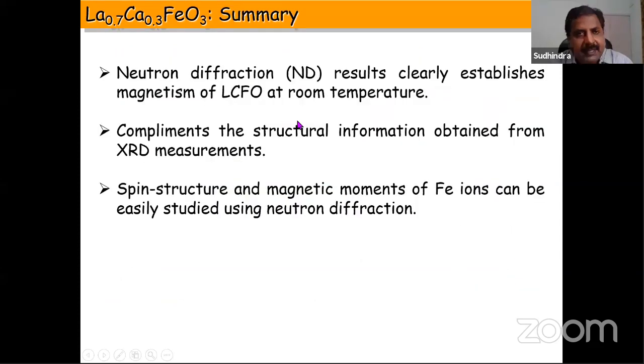So to summarize this part, I can say that the neutron diffraction clearly establishes that LCFO was magnetic at room temperature. There's no impurity in that. And the information obtained from neutron complements the information which we get from the X-ray measurements. And you can also look at the spin structure and magnetic moments of Fe, iron in this case.